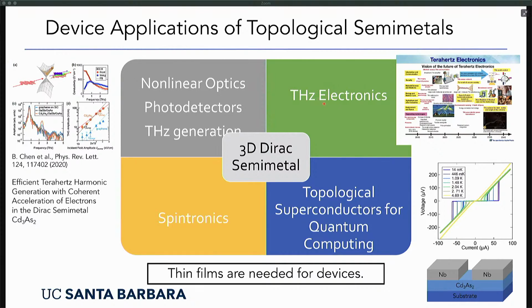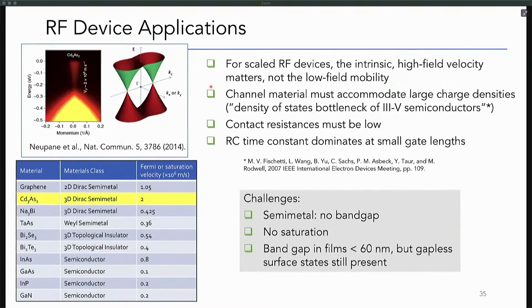But the one I wanted to talk about just a little bit with the remaining time is high frequency applications, so for transistors. The motivation for this is that cadmium arsenide has a very high Fermi velocity. If you look at this table and compare saturation velocities of different semiconductors, as well as Fermi velocities of different 3D TIs, Weyl semimetals, and also graphene, it actually has the highest Fermi velocity. So that promises high-speed applications, in particular in scaled devices, where the Fermi velocity is actually much more important than the mobility.